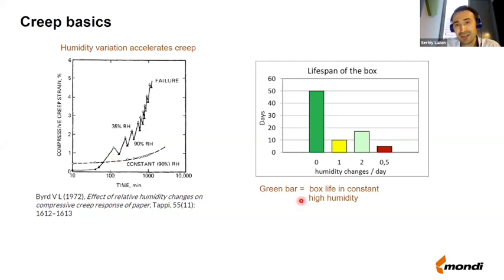And it is also interesting to look at this plot, because here you see how the lifetime of the box depends on how much the humidity is changing, or how many humidity cycles you have per day. So in the basic case where you have no changes in humidity, let's say the box can survive for 50 days. But once you introduce one cycle per day, then the lifetime of a box will go from 50 days down to 10 days.